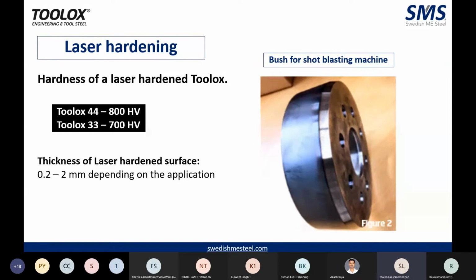The main advantage of having a laser hardened Toolox 44 is there is little distortion in the whole component. And since the laser hardened beam width is very accurate and to the point, your cutting edges can be done with this laser hardened edge, and that will give long lasting results. We shall see how it is useful in the application part when we go through it.